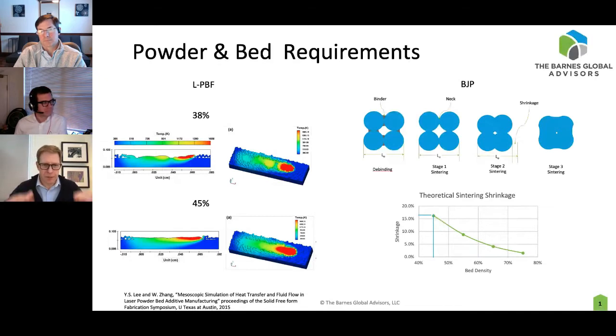The other thing that's simultaneously happening is that when that fluid's coming in, it's displacing air that's there. And it's easy to forget that there's actually a gas in the bed, which, in this instance, if it's 55% dense, it's 45% gas. That gas has to be able to escape efficiently. Otherwise, you're going to create additional defects.